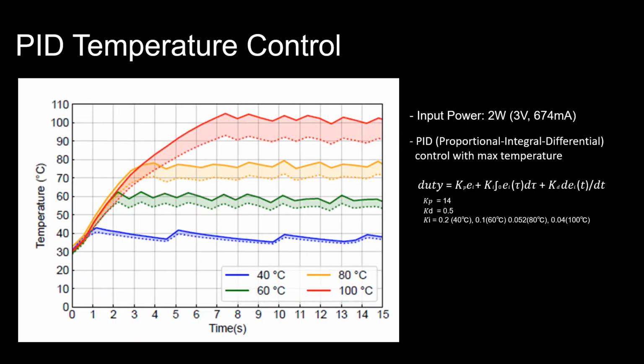While it was difficult to control the rapid heating ability of the carbon nanomaterial heater, we found we can control the maximum temperature at low voltage, around 3 volts, by using PID control. We empirically optimized the PID parameters and achieved stable temperature with ±2 Celsius degree deviation.